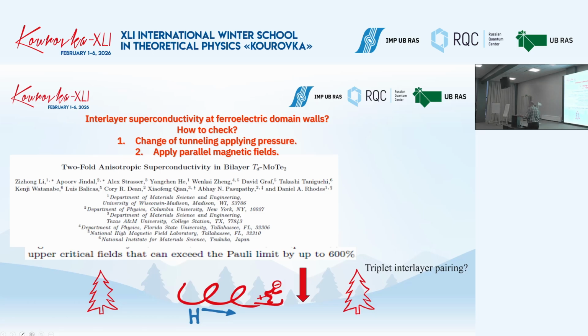Another way is to apply a parallel magnetic field to our structure, so as to change the transfer of electrons due to the vector potential, for instance. And these kinds of experiments have been done by the same group. And they observed two interesting, important things. First, they observed that the critical magnetic field applied parallel to the structure exceeds the paramagnetic limit. They exceed the Pauli limit. You see, 600%. Quite large. And this is a sort of indication that probably we should have some sort of triplet pairs here. In the same sense, it's a sort of argument in favor of the explanation which I have discussed.